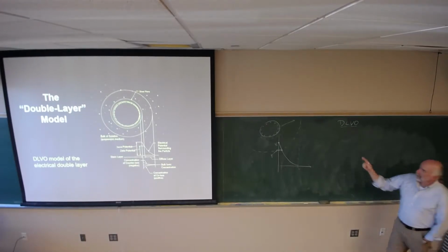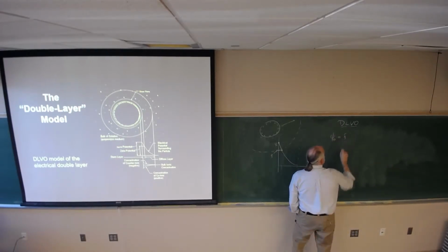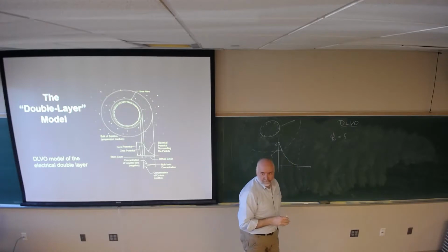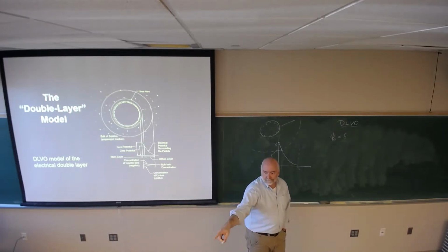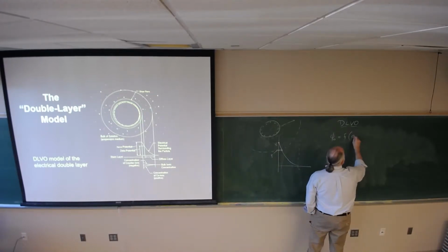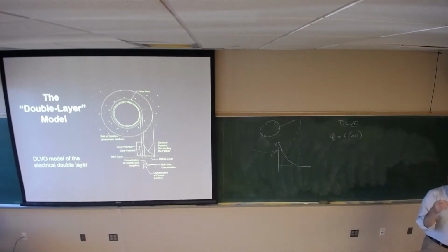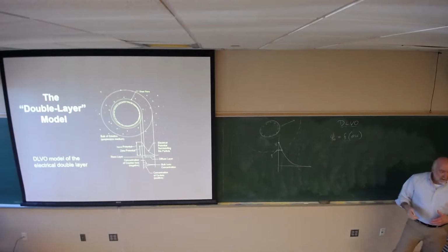The Nernst potential is a function of pH. I change the acid or base concentration in that suspension, causing reactions to occur on the particle surface. Depending on how I change that pH, I'll develop a net positive or net negative charge.